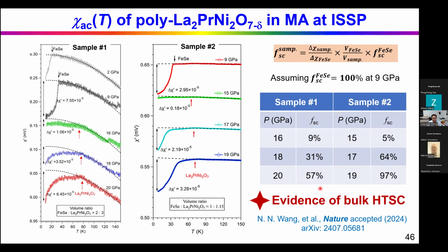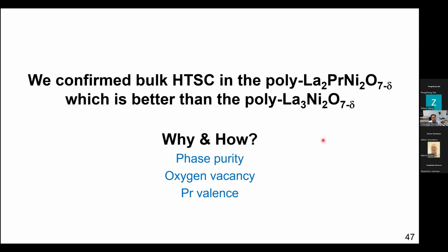But I want to mention that this is just a rough estimation, because for iron selenium, we are not quite sure whether it's 100% or not for these peculiar samples. But at least from this result, we are quite confident that it has a very large volume fraction for the superconductivity. It should be above high TC superconductivity.